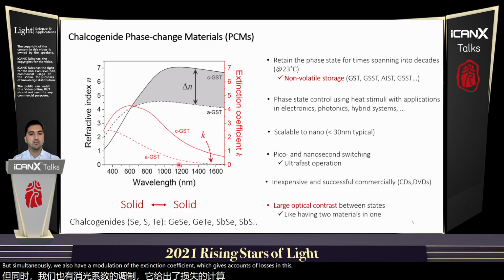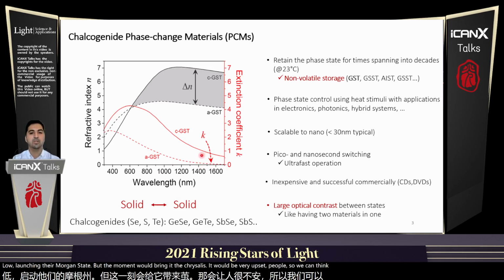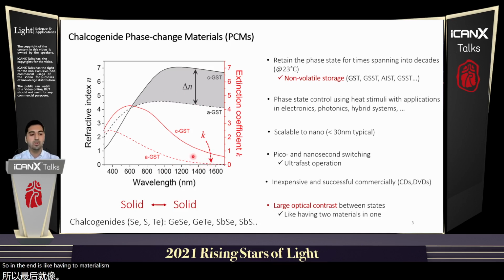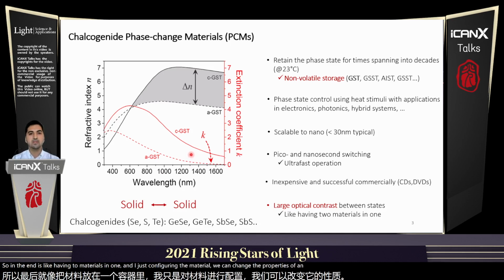So in this case, the amorphous GST is low loss in the amorphous state, but the moment we bring it to crystalline, it will be very absorptive. So we can think about amplitude modulation. So in the end, it's like having two materials in one, and by just configuring the material, we can change the properties of an optical system.